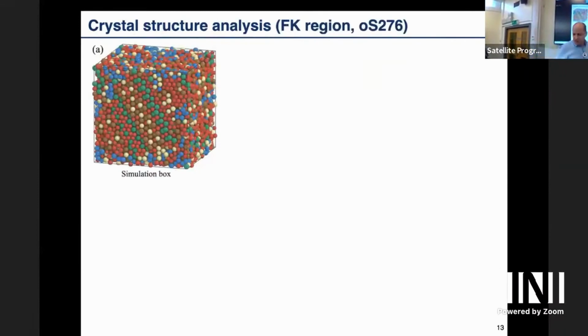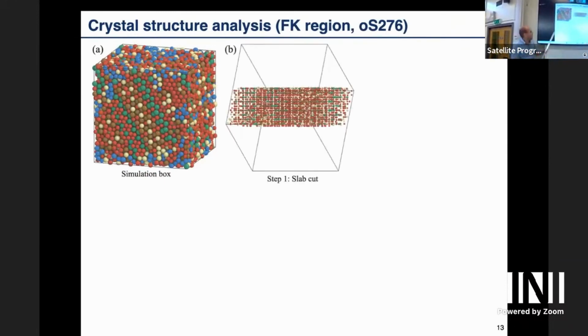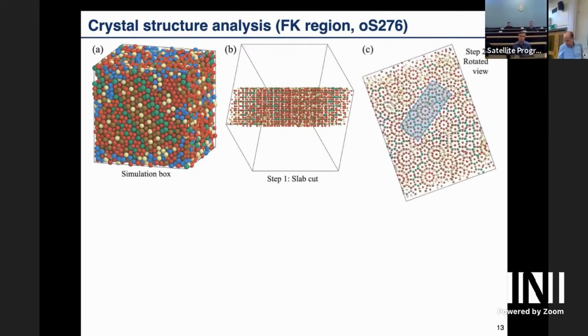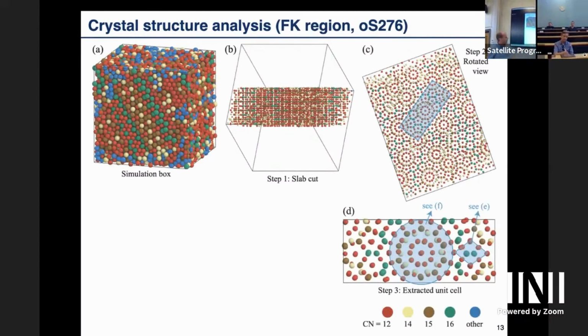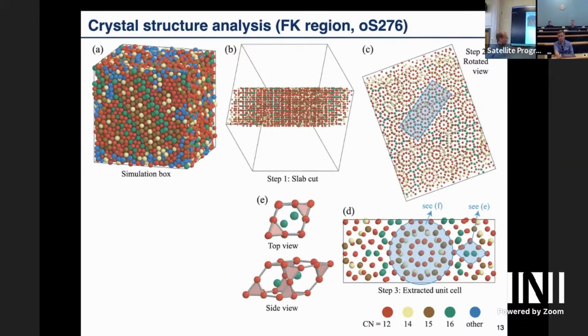And to get the image I just showed you, we can do this as follows. We start here with our sample. We then take a cut, essentially perpendicular to the layers. Then we rotate it around and look from the top. You see some structure here. When you look long enough, you see a unit cell, and you take out the unit cell. Then you see different features like this big ring and this small rhomb. The big ring and the small rhomb is something that's well known. This is actually the basic unit in a Laves phase.